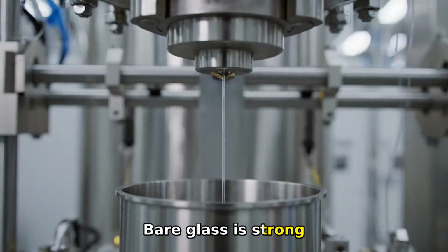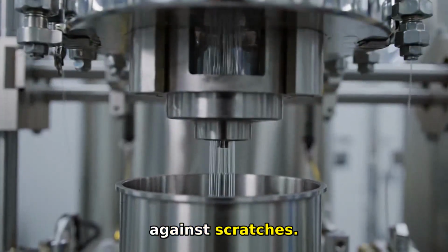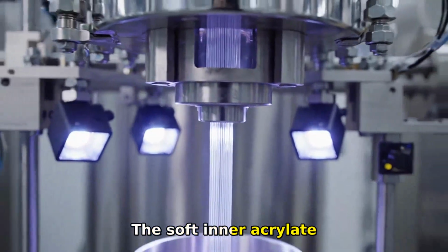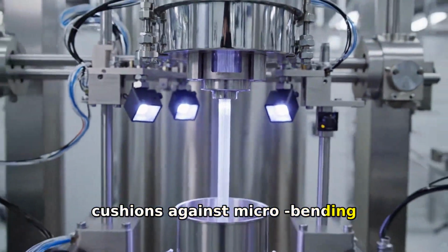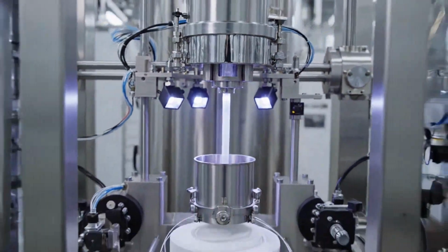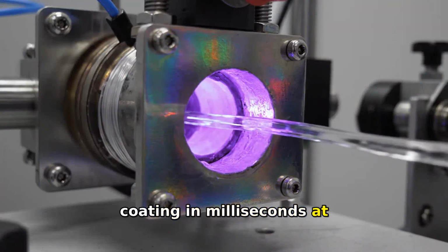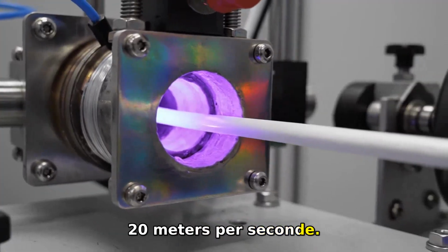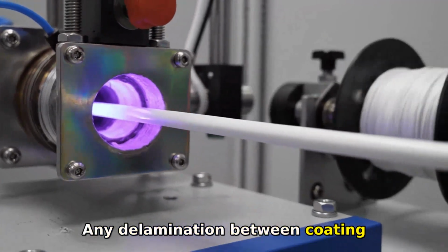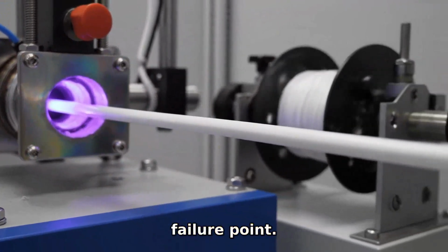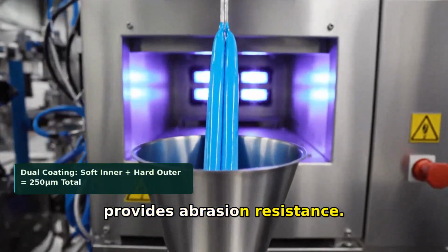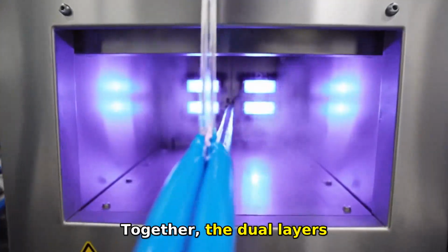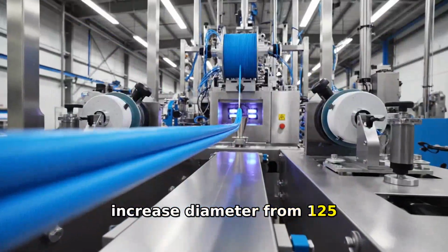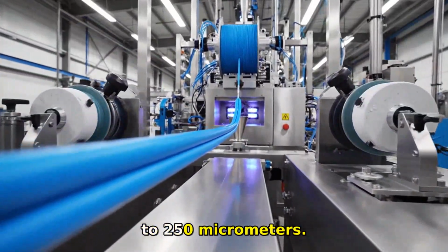Bare glass is strong in tension, but fragile against scratches. The soft inner acrylate cushions against microbending that causes signal loss. UV lamps cure the coating in milliseconds at 20 meters per second. Any delamination between coating and glass creates a failure point. The harder outer acrylate provides abrasion resistance. Together, the dual layers increase diameter from 125 to 250 micrometers.